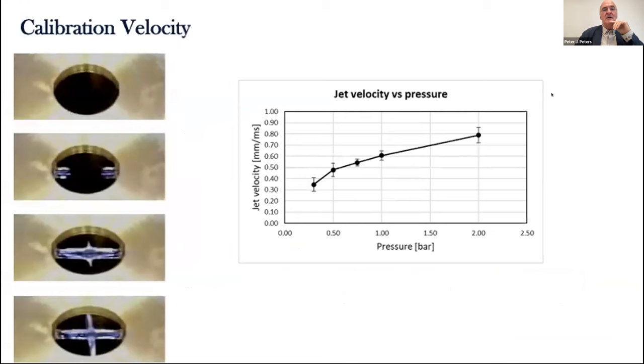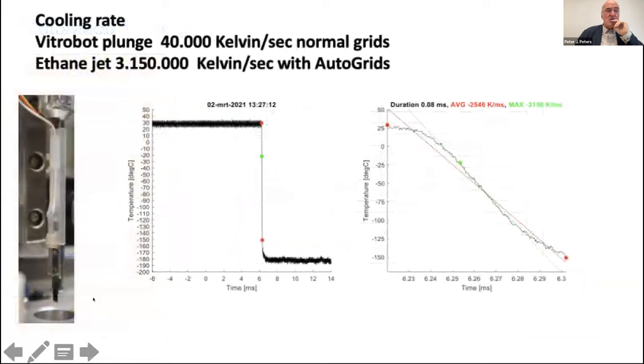Here we looked at pressure versus velocity. As you can see, if you go from 0.4 bar to 2 bar, you increase the velocity. We found that 1 bar is the best for our process. Here you can see some pictures of the jetting again. Here is the device to measure the cooling rate. This is a MEMS device that comes from another Dutch company from Delft.